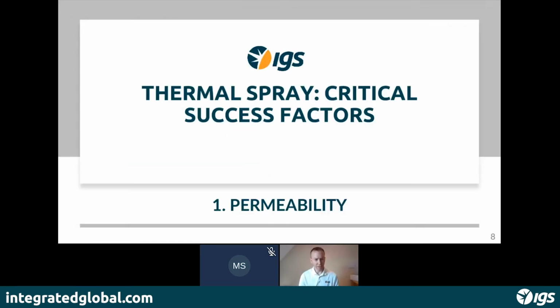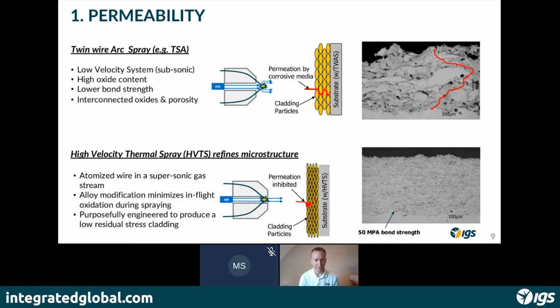So with thermal spray itself, I would imagine most of you have some experience of thermal spray, but that's likely to be with a system like thermal spray aluminium, which is used to externally protect equipment from environmental corrosion. Now, TSA can be used in situations where it's permeable. You have the aluminium in there as a sacrificial material to prevent the corrosion of the steel substrate. Where IGS are working, we're working inside the units and we're applying a higher nobility alloy. So we have to eliminate any permeability.